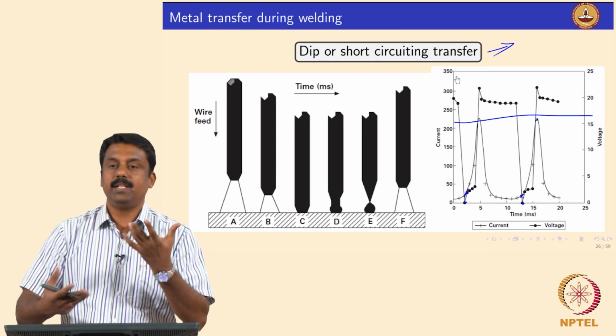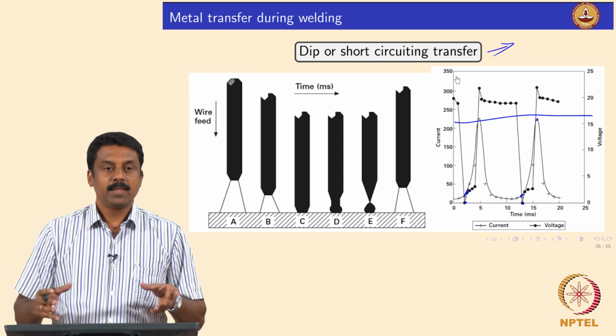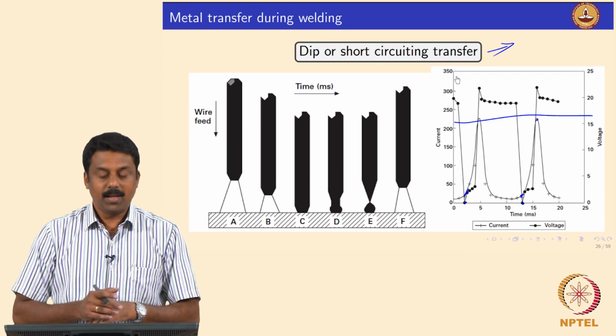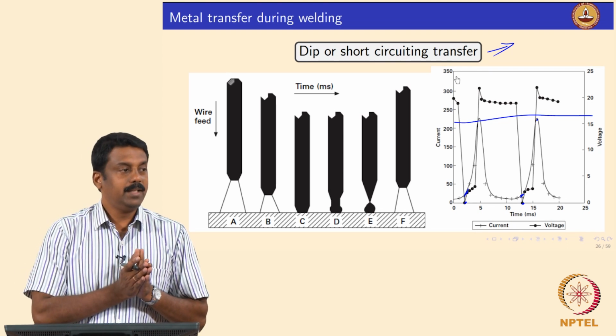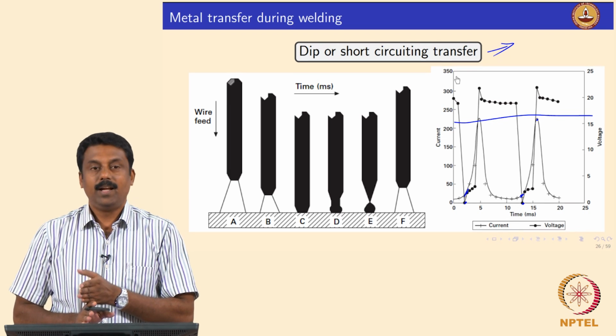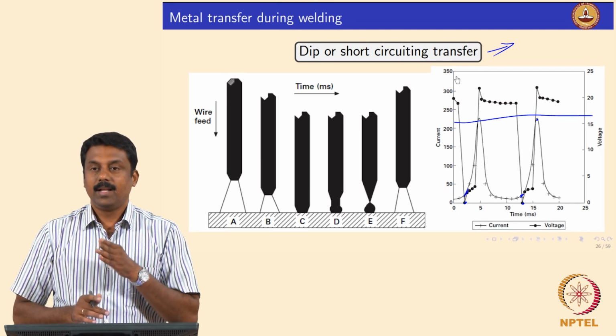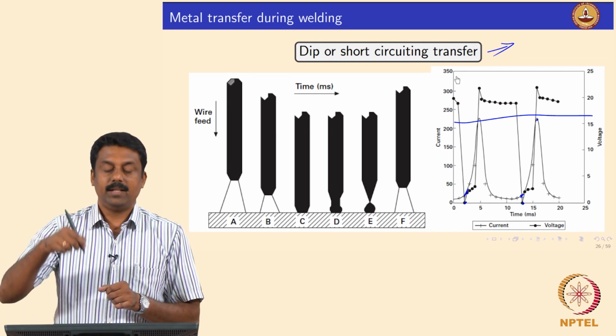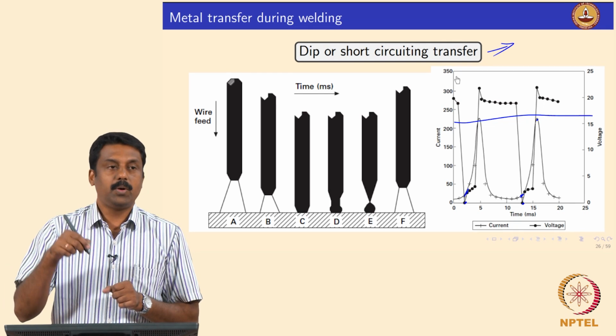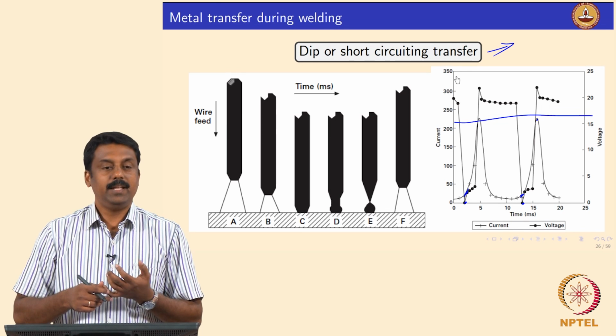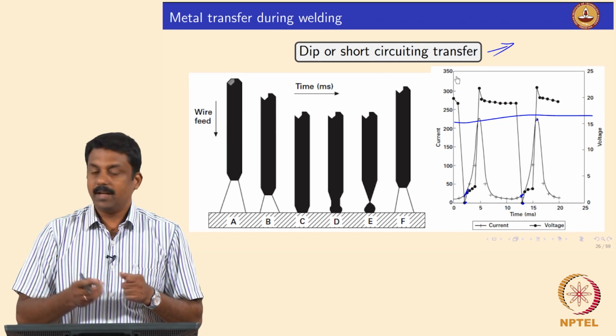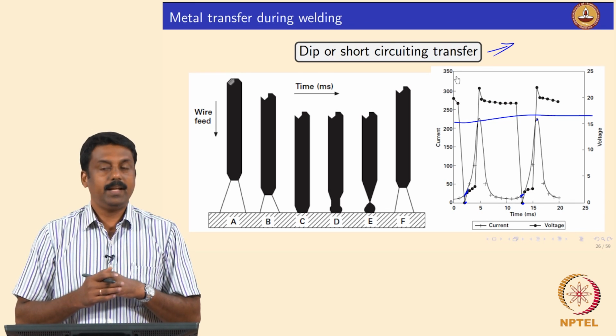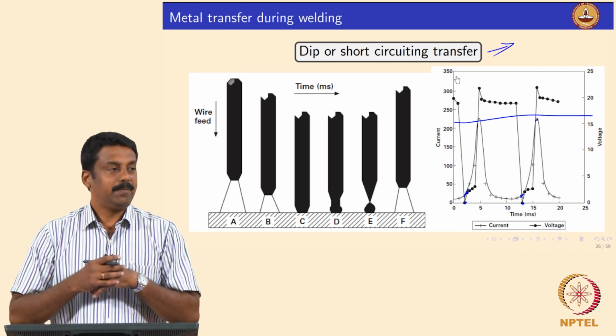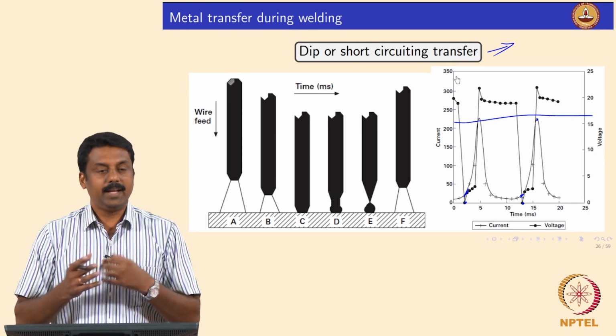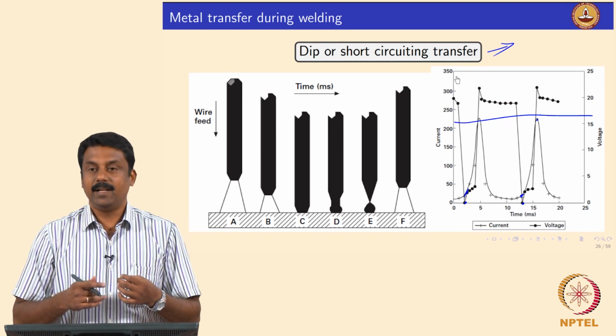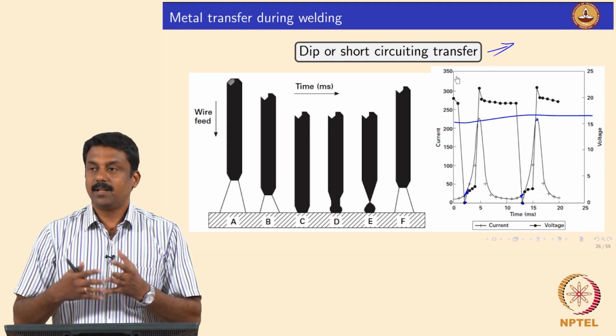We will see subsequently in advanced GMAW processes, when you look at the end of this unit, what complex waveforms we use to achieve this transfer. But the basics is this. What is the basic? The moment short circuiting happens, voltage becomes 0, and the power source identifies that moment, switches off the current, and subsequently the wire is retracted. So, the forward and reverse motion of the wire is controlled by controlling the feeding rate. And how does the feeding rate get controlled? By calculating the melting rate. Okay. So, the melting rate has to be calculated for a given diameter wire, for a given composition. So, then we can calculate the melting rate.